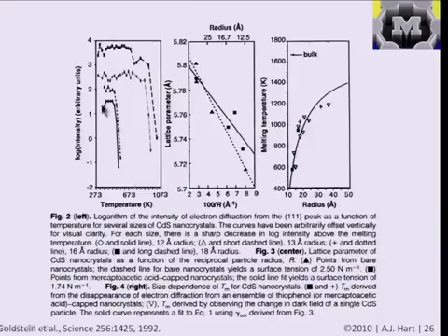So what they do is they look at the temperature at which the diffraction intensity decays for different particle sizes. And this represents small particles going up to larger particles. I think they have, for example, 12 angstroms or 1.2 nanometers, 1.3, 1.6, 1.8. Those are radius values. And as predicted by the theory, the melting point increases with size.